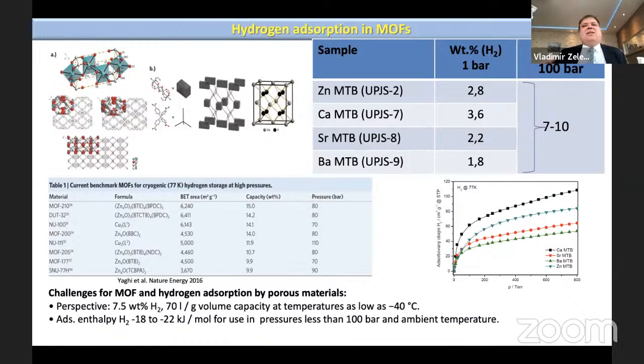A disadvantage of this material is that its absorption is a physical process using van der Waals forces. So this absorption is at cryogenic temperatures, at temperatures of liquid nitrogen. Now the scientists, and also we, focus on increasing this temperature, and the important thing is to increase the absorption energy, because usually the absorption energy of hydrogen on MOFs is between 5 to 10 kilojoule per mole. If we manage to increase this absorption energy to approximately 20 kilojoule per mole, such materials can absorb hydrogen also at ambient conditions, which will be this big challenge.